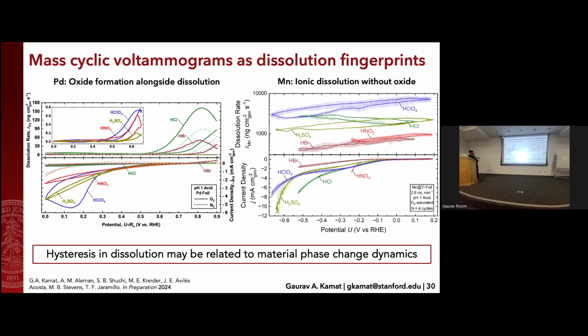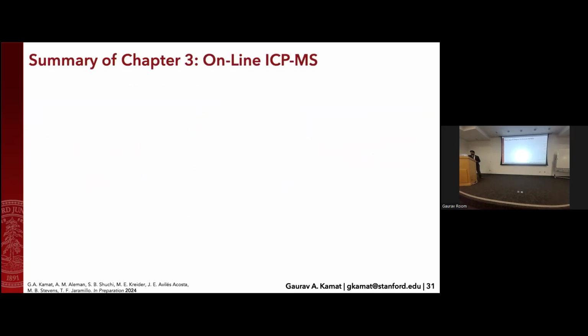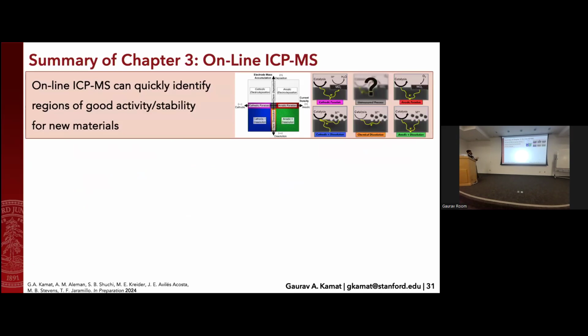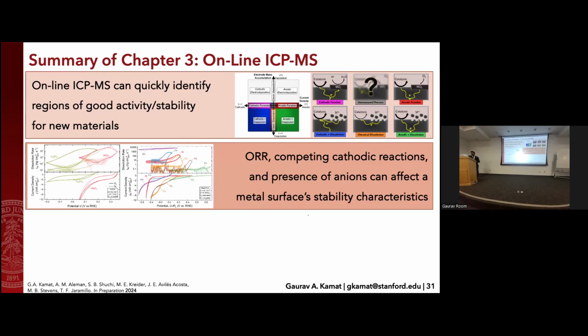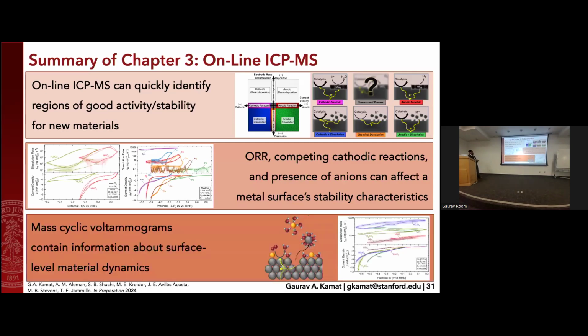So the hysteresis in your dissolution, which is the difference between the forward and the reverse sweep, can be related to some material phase change dynamics. So to quickly summarize, online ICP-MS can identify regions of good activity and stability for brand new materials that no one has really ever tested before. You have ORR, but also other competing cathodic reactions in the presence of anions that can affect a metal's surface stability. And you have mass cyclic voltammograms, which are these shapes here that contain some information about surface level material dynamics. So a very powerful platform in order to study new types of electrocatalysts and all their interactions.